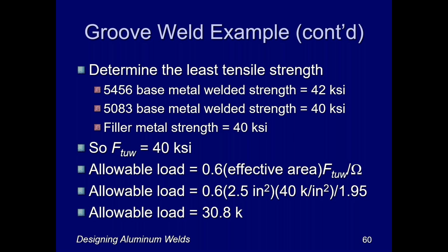One more thing, though, that you need to be aware of, and that is that for PJP welds, once we've calculated the allowable load, we need to factor it by 0.6. In other words, we need to reduce its strength by 40% because of the notch effect of not having fused metal at the base of the joint. Therefore, I apply that 0.6 factor times the area of the weld, 2.5 square inches, times the 40 ksi strength. I divide it by a safety factor, which for building structures is 1.95, given by the Specification for Aluminum Structures. And that gives me an allowable load of just shy of 31,000 pounds, or 31 kips, a kip being 1,000 pounds.